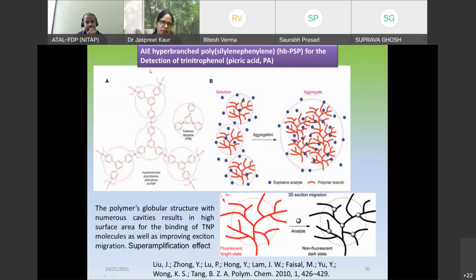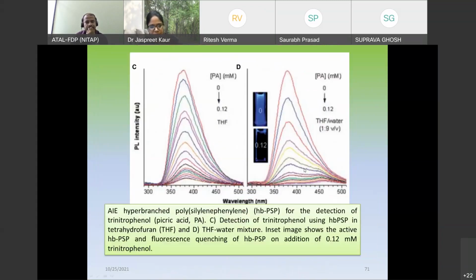So here you can see aggregation induced emission in hyperbranched polysilane phenylene compounds. So these are silicon-based compounds. These are hyperbranched polysilane phenylene, HBPSP compounds. So these are used for the detection of picric acid. So they show aggregation phenomena. After the aggregation, you can have better binding with the TNP. So this is also called the super amplification effect. So this is the aggregation induced hyperbranched HBPSP for the detection of picric acid.